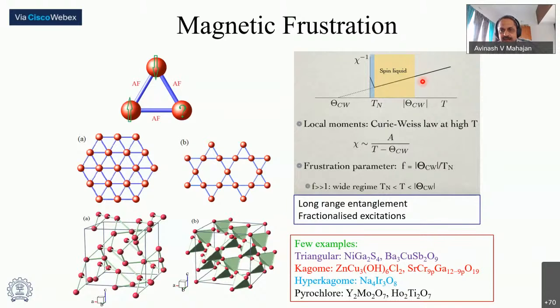Look if it has a Curie-Weiss behavior with a negative theta, suggesting antiferromagnetic interactions between the magnetic moments, and look whether there is any evidence of long-range ordering through a sharp peak in the susceptibility, at whatever temperature. So if not, then maybe you have a significant region in this temperature range where you expect spin liquid type